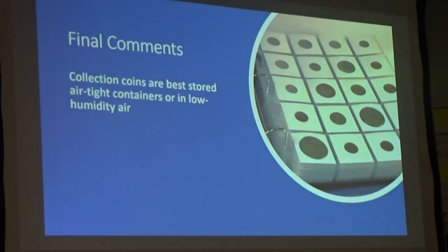Those are the major reactions — there are many others, but these are the main ones reviewed here. Final comments: coins are best stored in low-humidity environments in closed containers. Putting them in a current-day manufactured flip is a good way to prevent environmental chemicals from too rapidly getting to the surface. The older polyvinyl chloride flips — no. But present polyester-containing flips are good, as polyester does not interact with metals at all.